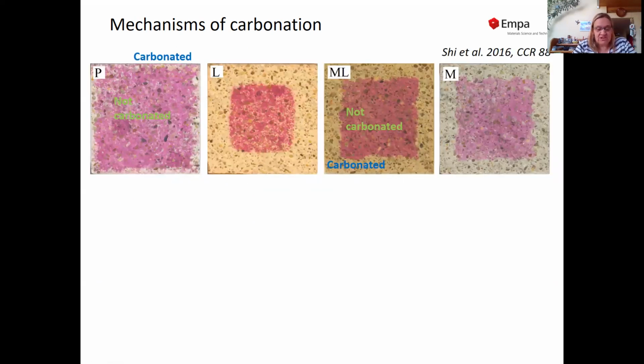If we now change to the experimental data, this is phenolphthalein sprayed upon the surface of carbonated specimens. We have on the left-hand side the Portland cement, we have a Portland limestone cement, and different Portland cement limestone with metakaolin mixes. What we can see is that we have a very small carbonation in the case of Portland cement, as we can see here, basically from the color change to colorless, much more in the limestone sample, and somewhat more in the metakaolin containing samples.